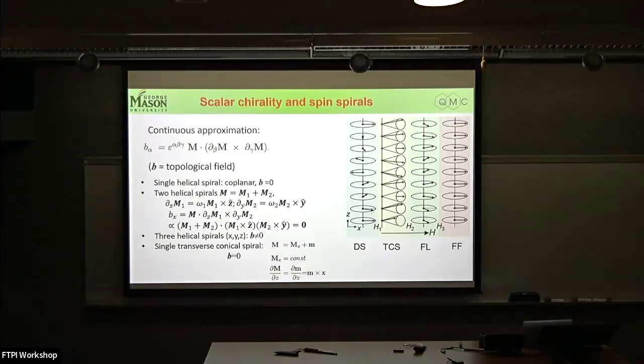And it's, again, very well known that in zero field they form this standard helical spiral. Now, when you apply magnetic field in the plane, at first the spiral starts distorting a little bit. Its differential susceptibility is low. At some point, you have a spin flop, standard spin flop. So this helical spiral flops into a cycloidal, canted cycloidal spiral, or also called transverse conical spiral.